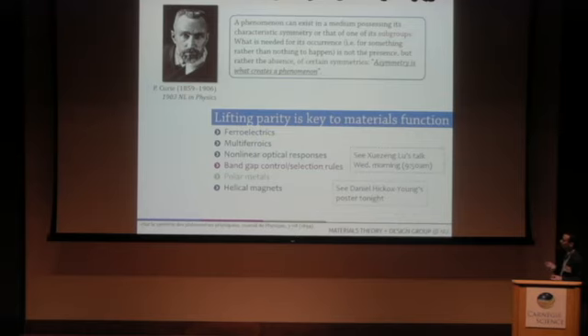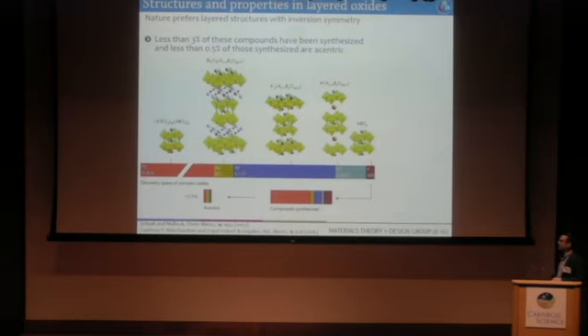So what we're doing is trying to think about ways to lift inversion symmetry. And what I want to do is take a survey of what's possible in terms of crystal chemistry of perovskite-derived structures. So these are structures which exhibit corner-connected octahedra in 2 or 3 dimensions. And so this is a survey of the ICSD back in 2016. And what I'm showing you is the potential landscape of possible compositions that you could have by just ordering different chemical species, maintaining charge neutrality.